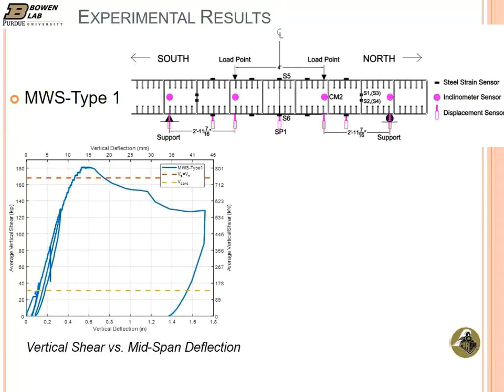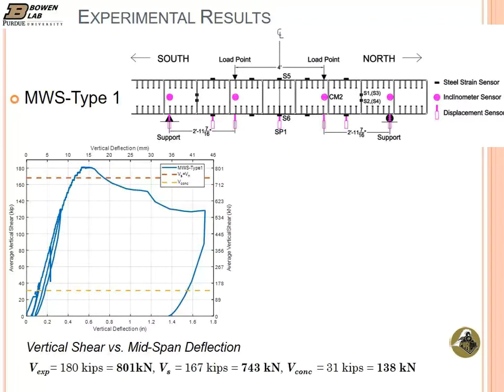This is the load displacement response for the type 1 specimen. You see an initial linear response, and then some nonlinearity as we had shear cracks towards the peak point, and then a sudden failure. It was a brittle failure mode due to concrete crushing. The experimental strength was about 800 kilonewtons. If you compare with the code equation, for this case you take the larger of either the concrete or steel, because the spacing is larger than T/2. The shear reinforcement spacing is equal to T, so you take the larger, and we get 743 kilonewtons. So the experimental strength was larger than the code calculated strength.